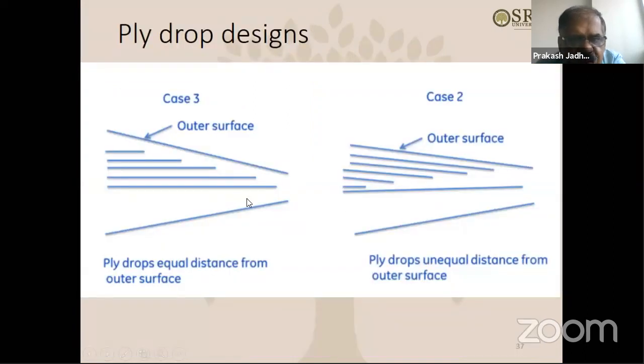So what is the difference between case two and case three? As you can see, the ply drops are equidistant from the outer surface. So basically what is happening is, you have a variable thickness specimen here. The left end is 48 plies and the right end is 38 plies, and the plies are getting dropped along the way. So there will be 10 plies dropping from 48 to 38. We can design the coupon so that 5 plies are dropping at the top and 5 plies are dropping at the bottom, so a total of 10 plies are dropping. So we'll have 48 at the left end and 38 plies at the right end.